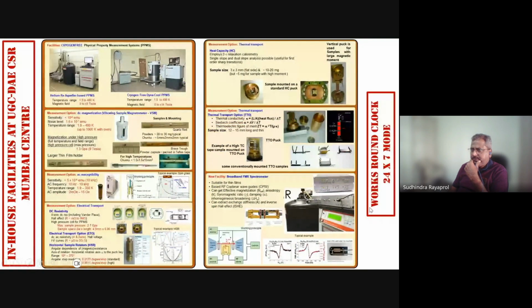Okay. In addition to neutron diffraction, we have what is known as physical property measurement systems. We have one cryogen-based as well as a cryo-free system with a magnetic field up to 14 Tesla. And there are a lot of measurements which are possible. You can do DC magnetization like with a VSM. We have an AC susceptometer. You can do AC susceptibility measurements. Of course, the temperature range and field range remains the same for all the measurements. We can do DC resistivity, electric transport like ETO, Hall voltage measurements and all.